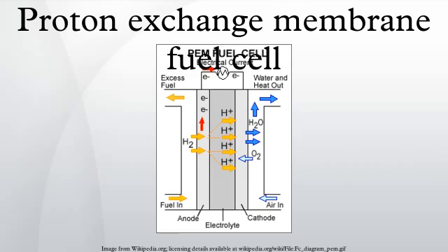A second method of increasing the catalytic activity of platinum is to alloy it with other metals. For example, it was recently shown that the Pt3Ni(111) surface has a higher oxygen reduction activity than pure Pt(111) by a factor of 10. The authors attribute this dramatic performance increase to modifications to the electronic structure of the surface, reducing its tendency to bond to oxygen-containing ionic species present in PEM fuel cells and hence increasing the number of available sites for oxygen adsorption and reduction.